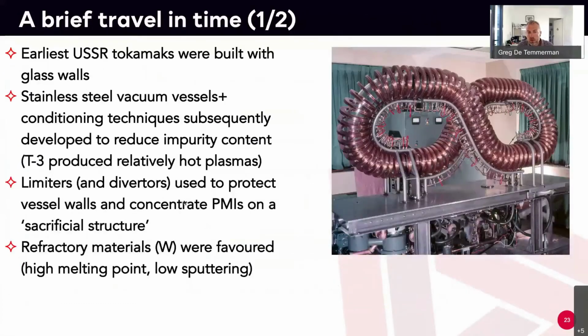If I look back in time, how things happened, very early on, the first tokamaks and the first fusion devices were built with glass walls. You might wonder why, but it's because glass was actually easy to manufacture in different shapes. You see a first example of a machine. So there is no scale, but it's about a meter across. And you see that this is basically a glass tube, and you see the magnetic coils around.